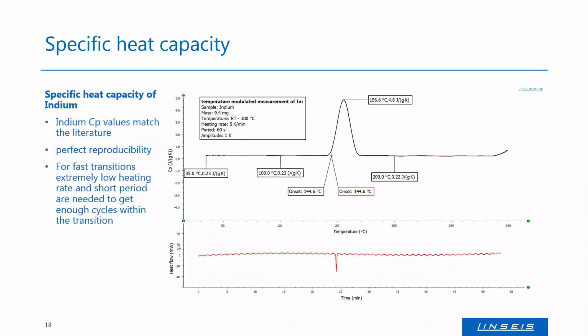Okay, normally we should choose a calibration material that's almost similar to our sample. So if you measure, for example, a metal, you should calibrate with a metal and not with a polymer, because the heat capacity and mostly also the weight are really different here. But I want to check if it's still possible with the chip DSC and temperature modulation to get valuable CP values here if I measure some metals.